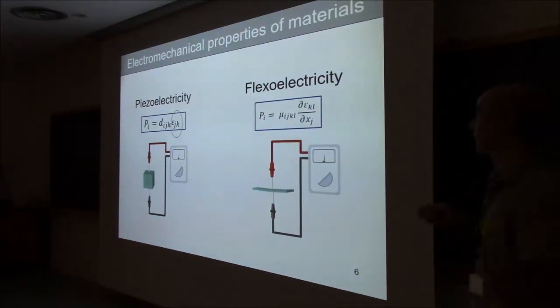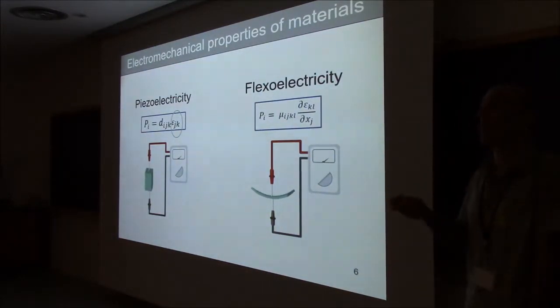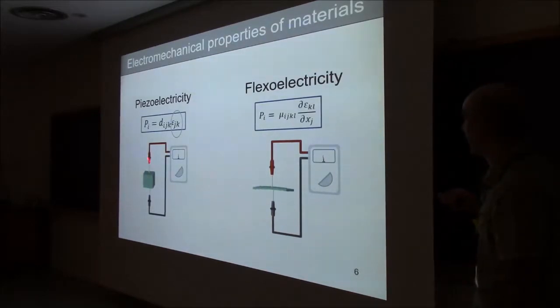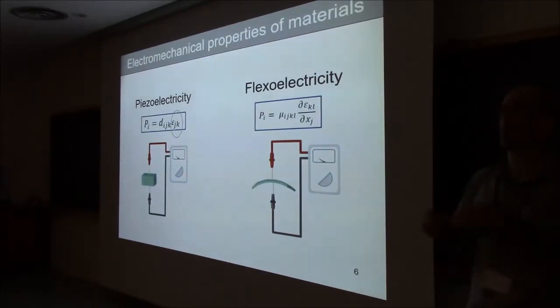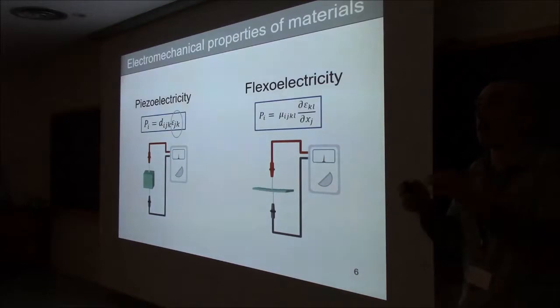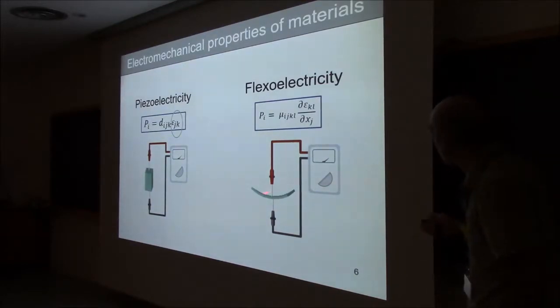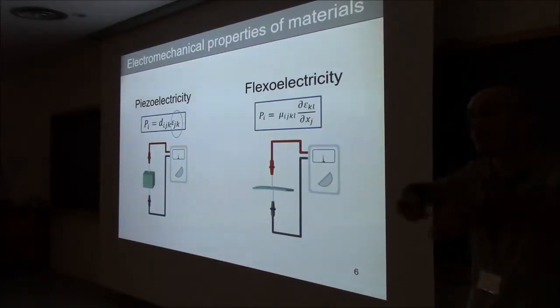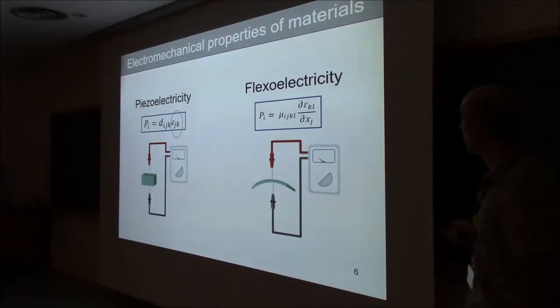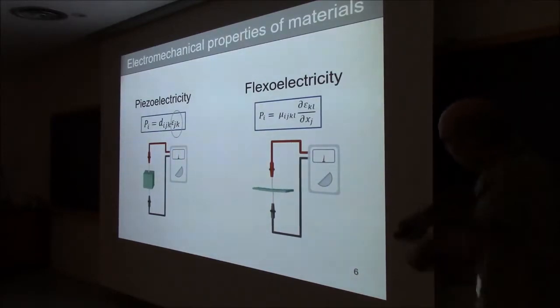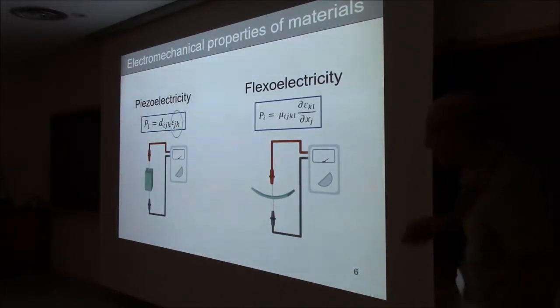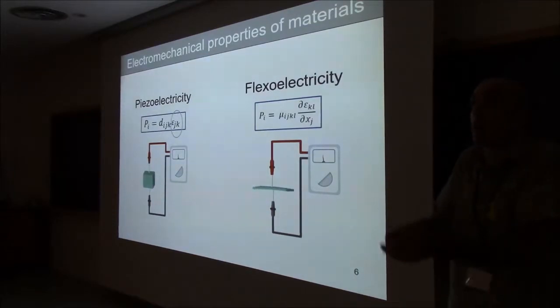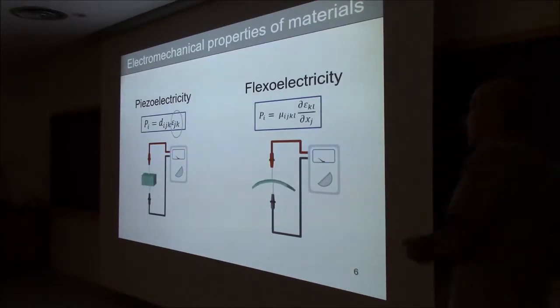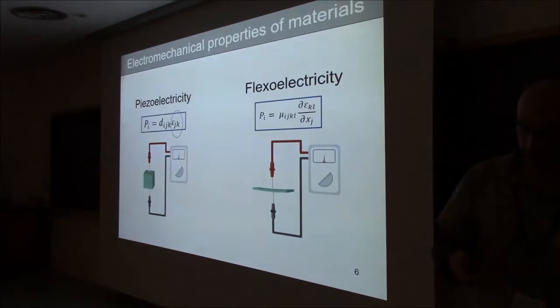If you want to measure flexoelectricity, what you do instead is, instead of applying a homogeneous compression, you can apply, for example, a bending. A bending will give you compression on the concave side and extension on the convex side. Okay, so when this is pointing down, this side is compressed, this side is extended, so you will have broken the symmetry just by bending.